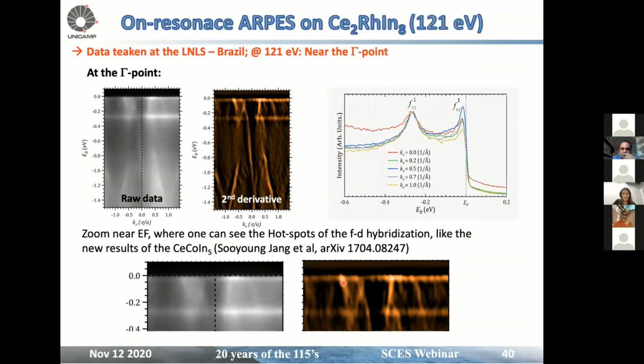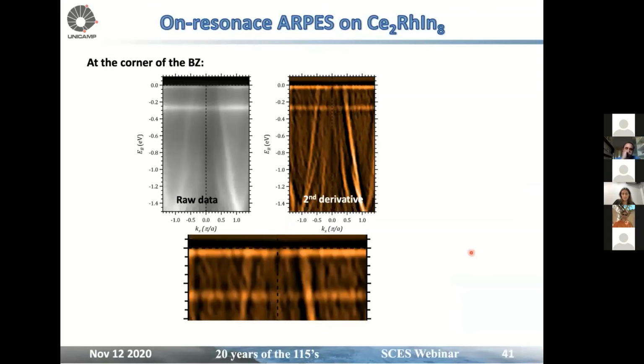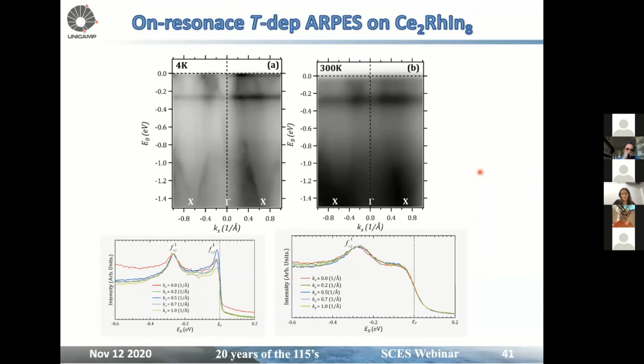But unfortunately, I don't have those measurements as a function of temperature. I can only show you that if we move around K, we see a bigger 4f peak near the bands that cross the conduction bands at those spots. This is just the corner of the Brillouin zone, where we are still seeing the effects. And finally, I compare low temperature data with high temperature data, where we cannot see any hybridization peak near EF, but unfortunately I don't have a temperature evolution to try to set the Kondo scaling for that compound. So a strong peak near EF at low T that disappears at 300 K is evidence of f-d hybridization.